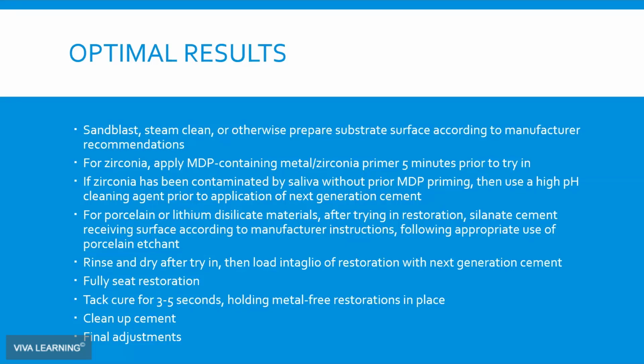After the surface has been cleaned and the intaglio has been loaded with the next-gen cement, then the restoration is fully seated. I like to hold the restoration in place. Ever since we got rid of bevels on our preparations, I find that the restoration does fit, it is stable, but I find you can rotate it or wobble it just a fraction, a degree or two. Well, that degree or two can cause problems, either open contacts, high spots in your occlusion, whatever. So I like to physically hold it in place while my assistant or with my free hand, I will tack usually the buccal surface for about 3 seconds. Then I'll let go and tack the opposing side and then begin cleanup.